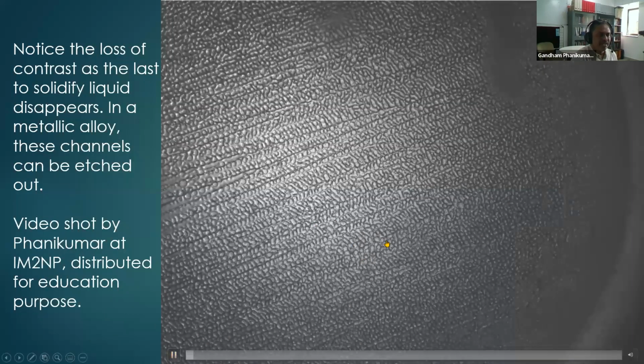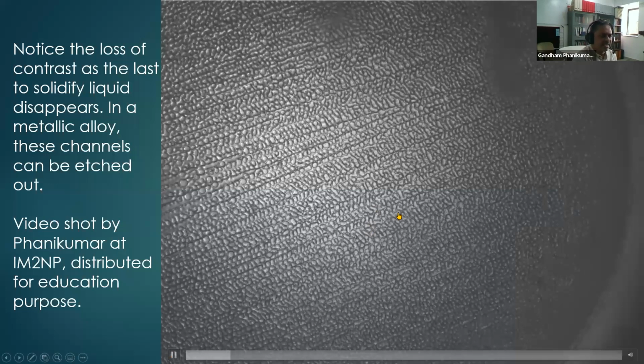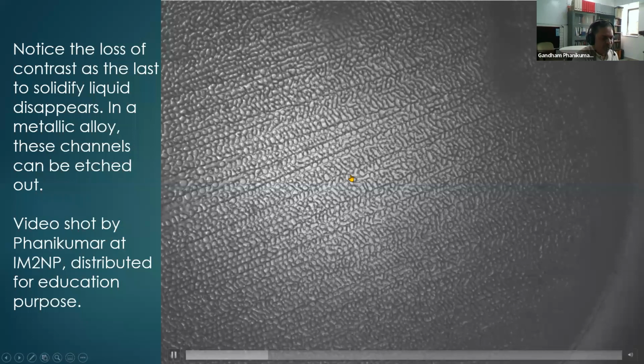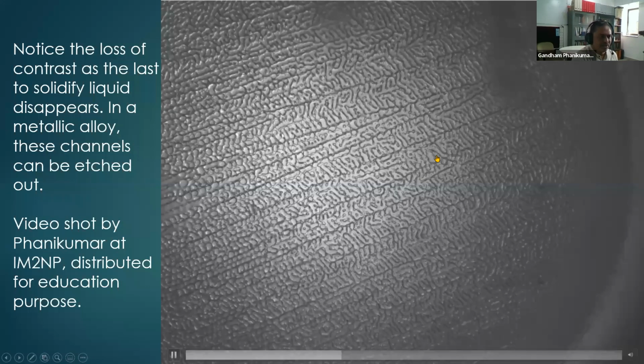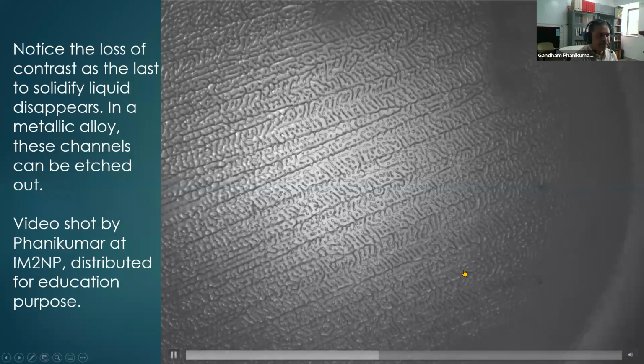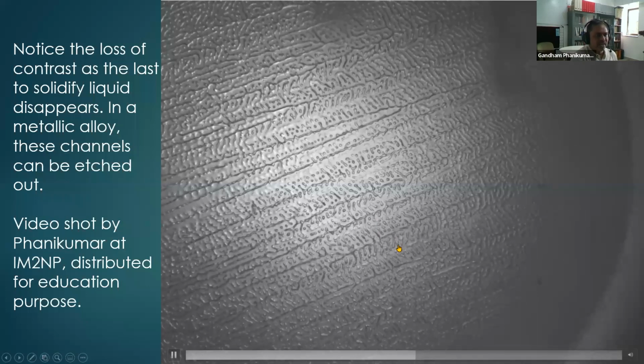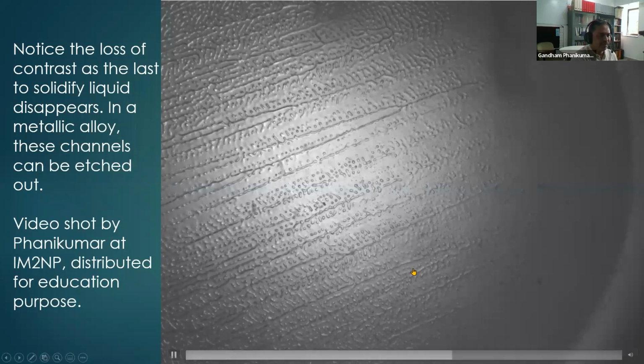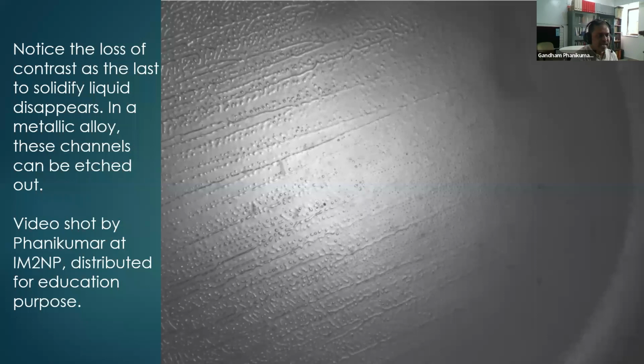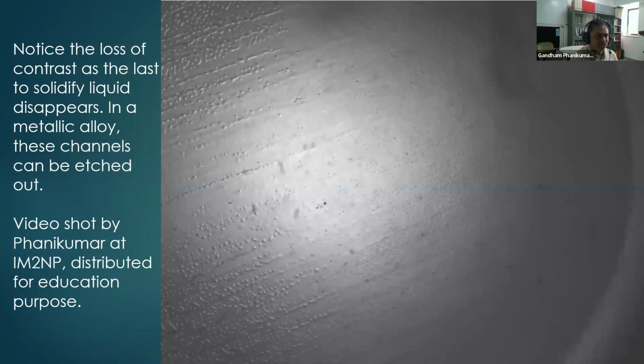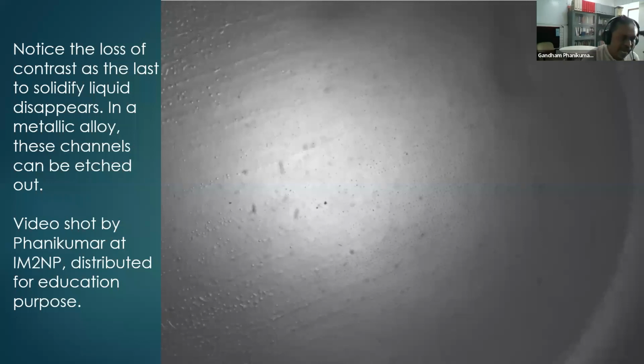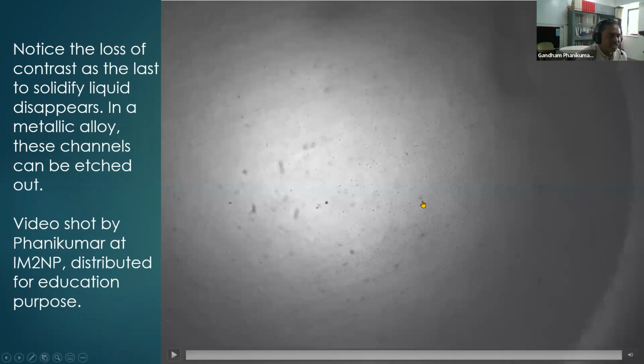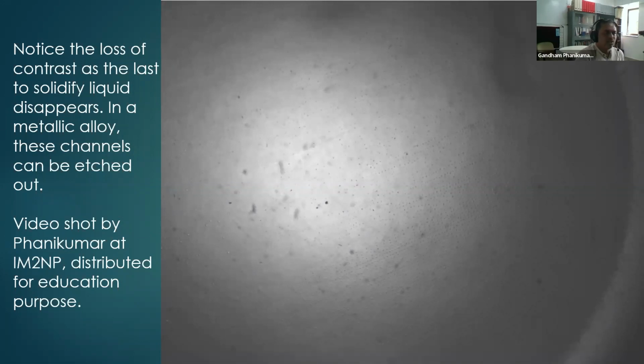Now, when you wait for the solidification to finish, you will see that the interdendritic region will start to merge with the rest of the solid, and therefore these patterns will start to disappear, because the liquid is finishing off its solidification. At some point it becomes just a few dots of interdendritic liquid, and they will also finish solidifying, and eventually you will see no contrast because it is all fully solid. So this is how solidification happens in reality, and the original regions of liquid are available for us to know because the segregation has happened, and therefore one can etch and find out where they are.